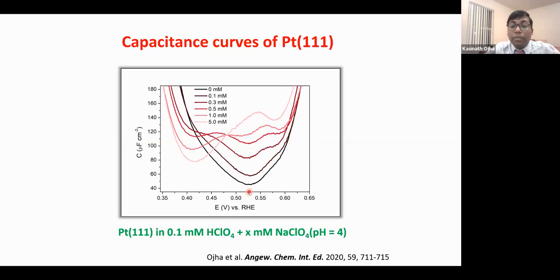But this is a minimum which follows with ionic strength, and that exactly follows the Gouy-Chapman theory. It's a very exciting result. So there we confirm that this potential corresponds to the potential of zero charge of the platinum, and it's exactly matching the potential of zero charge which is derived from other methods by other groups.